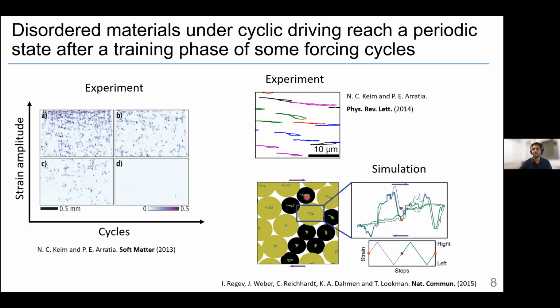In experiment and simulation, if you look at the particle trajectory, you can see that they form loops in space. This is experimental data. This is a simulation, and you can see the trajectory that the particle goes through. If you look carefully, you can see that this is a multiperiodic cycle. You start at this orange dot, you do one cycle of driving, you reach the purple dot, and after another driving cycle, you return to the orange dot again. So the response is as follows. You start at low strain amplitude, and the response has a periodicity that equals the periodicity of the driving. When you increase the strain, you reach higher and higher periodicities. And when you surpass some critical value, you don't get any periodic state at all, and the material just flows.